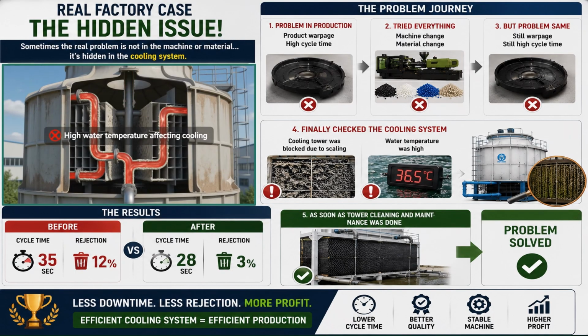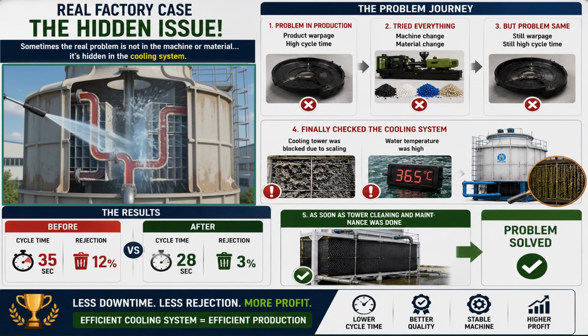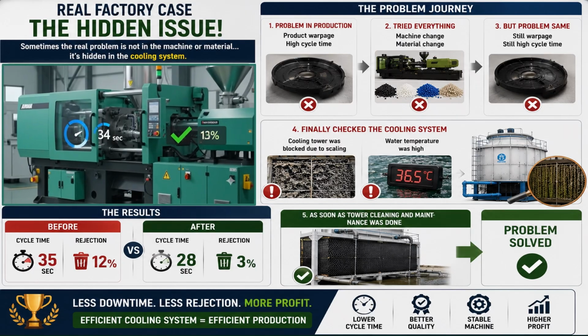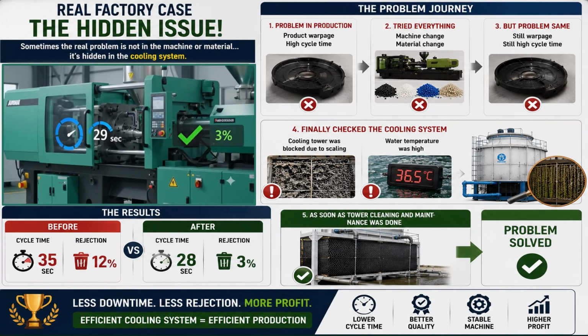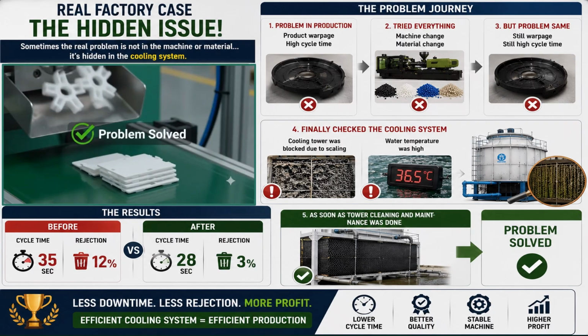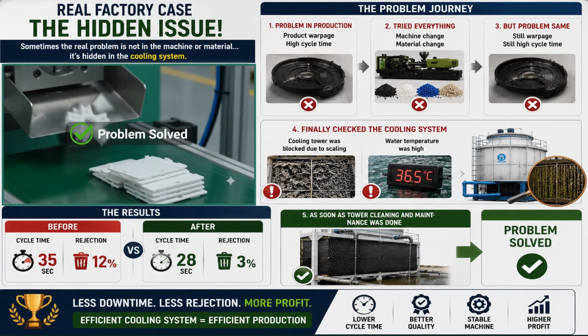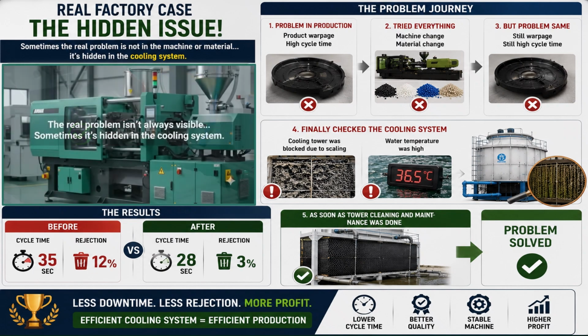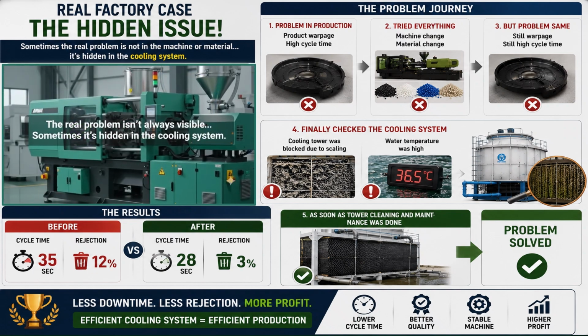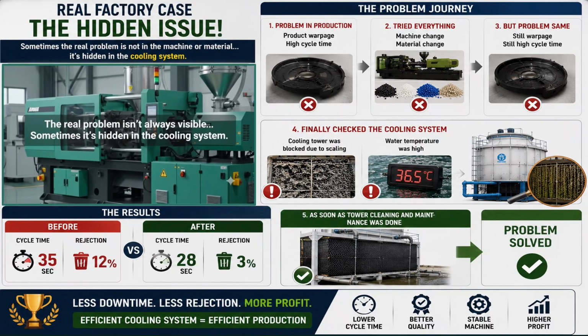Here's why. The cooling tower was blocked due to scaling and the water temperature was too high. As soon as proper cleaning and maintenance was done, cycle time dropped from 35 seconds to 28 seconds. Rejection reduced from 12% to just 3%. Problem solved. See, sometimes the issue isn't in the machine or the material. It's hidden in the cooling system.